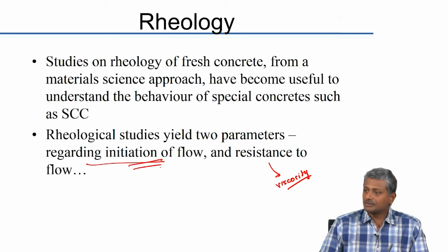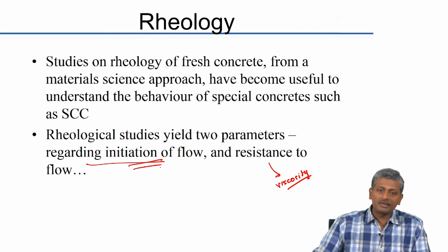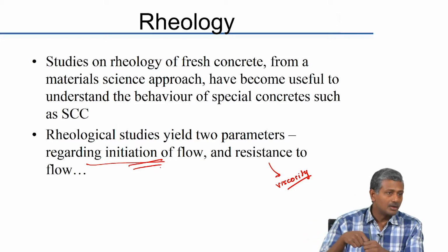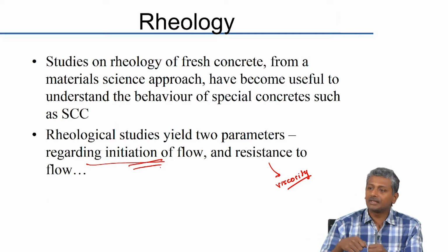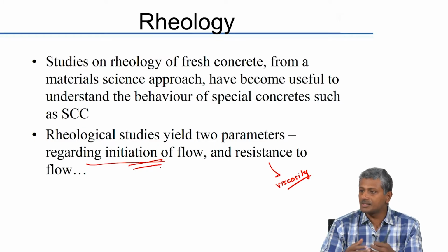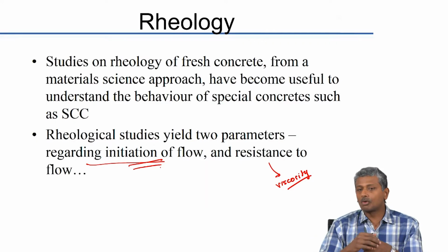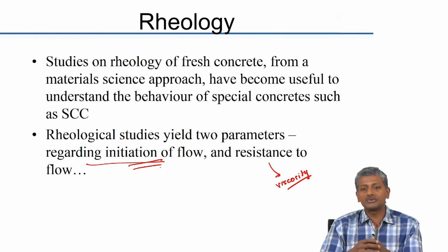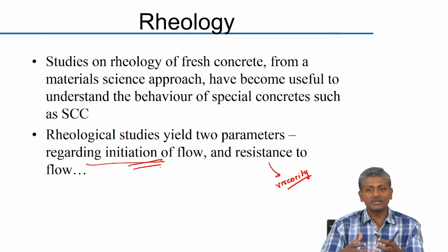Now, how is this relating to real life? For example, you put a concrete inside a formwork, this concrete does not go anywhere until you start vibrating it. So, the vibration creates the initiation of flow, and the concrete workability, which is your consistency, leads to the overall flow after the flow has been initiated. So, vibration essentially overcomes this initial build up, which is the innate shear stress that needs to be overcome in the material to make it start flowing.